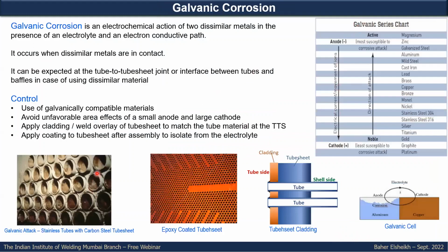For galvanic corrosion, you can see here the preferential attack of the tube-to-tube sheet joint, and it is not something uncommon. You can see this in the industry. As we mentioned earlier, you might apply cladding to avoid the dissimilar metal, so you will not have the potential differential which causes galvanic corrosion. In some cases you might apply special coatings like epoxy coating to the face of the tube sheet, and also the tubes. In many applications it is applied, and this has a good effect on eliminating or mitigating galvanic corrosion.